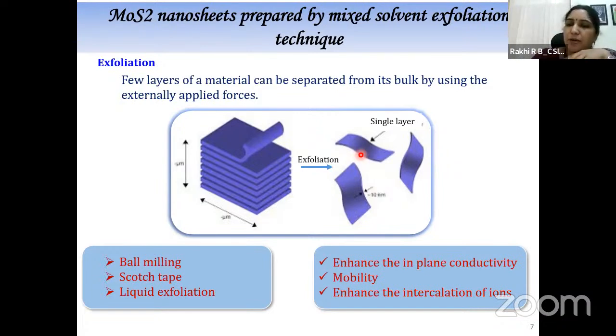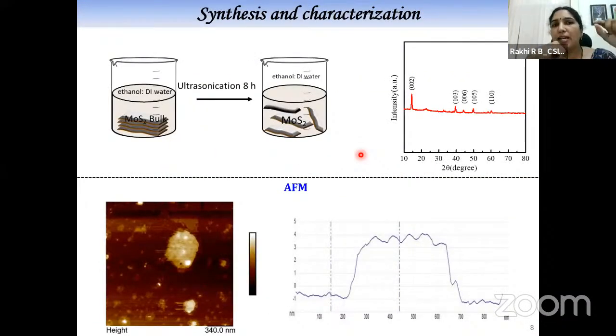What we have done is that we commercially purchased some MoS2 chunks, and then subjected them to solvent ultrasonication for 8 hours, and finally we obtained some powder from the bulk. As prepared, this was the 2H hexagonal system of MoS2 with the space group P63/mmc. After ultrasonication, we did XRD analysis on the collected powder, and there was no change. Then we did AFM to find out the number of layers in the different flakes of MoS2, and found that the average number of layers was nearly 4.